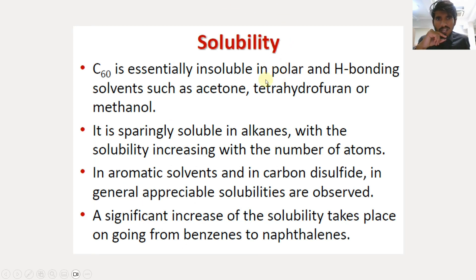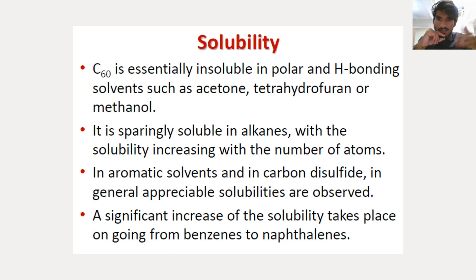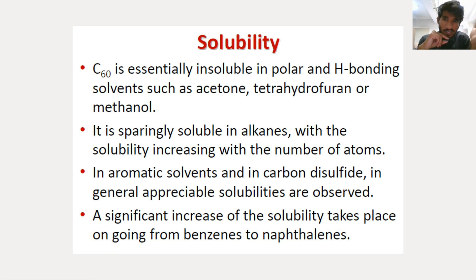C60 is essentially insoluble in polar and hydrogen-bonding solvents such as acetone, tetrahydrofuran, or methanol. It is sparingly soluble in alkanes, with solubility increasing with the number of carbon atoms — for example, C60 is less soluble in butane than in pentane. In aromatic solvents and carbon disulfide, appreciable solubilities are observed. A significant increase in solubility takes place going from benzene to naphthalene.